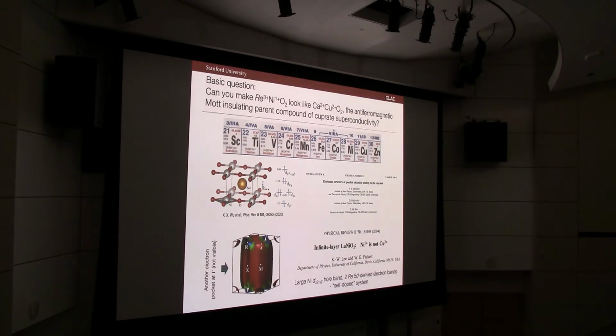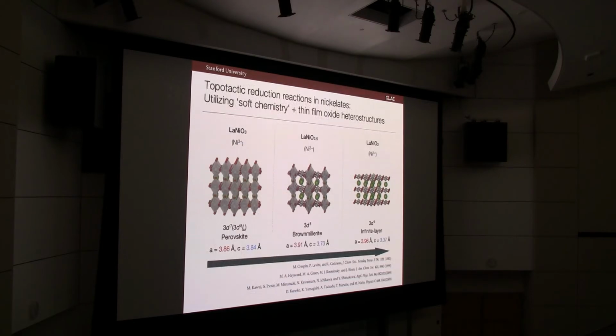Now for those of you with more of a materials or chemistry orientation, you'll immediately say, hey, this is very, very strange, right? Monovalent nickel is not something that is common or should be thermodynamically stable, and indeed it doesn't seem to be the case. This is a chemistry-oriented periodic table, so here's kind of the principal oxidation states. So nickel likes to be 2+, like nickel oxide. At high oxygen pressures, it can go to a 3+ state, and we want to make something really extreme and different from that. So how is this possible?